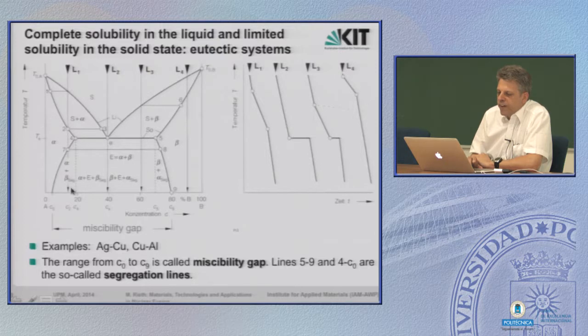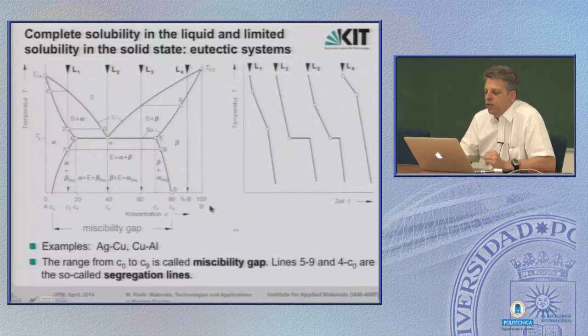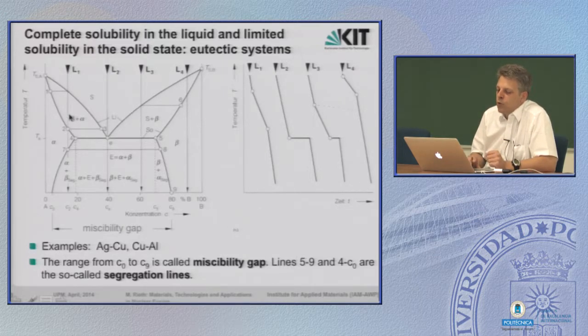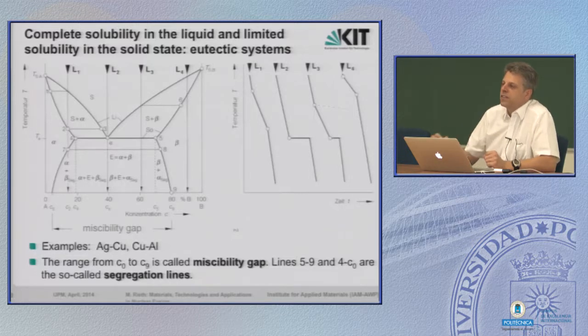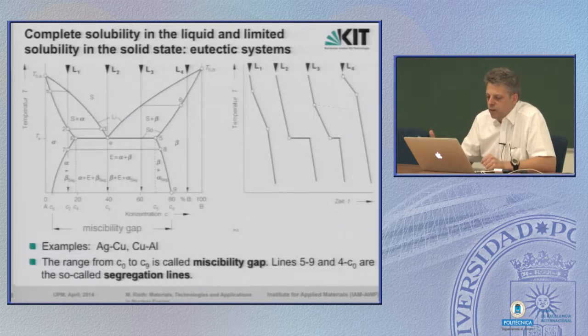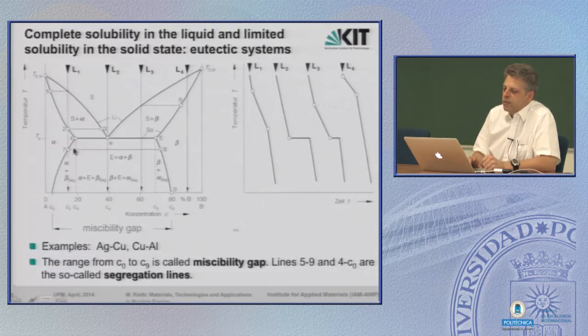Let's have a look here. What happens if we cool down with a composition along this line? First, again, the transition into solid and liquid state. Here, the solid state is a solid solute. That's a specific mix of pure A and pure B component. So that's again a crystal lattice. And then we reach a smaller area here in this case where the whole thing is solid, an alpha crystal, solid solute crystal.